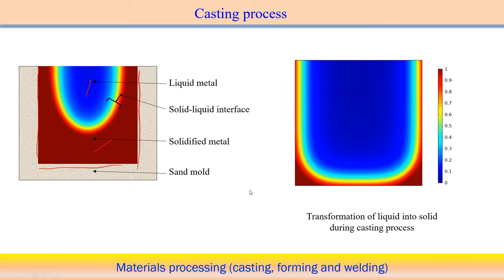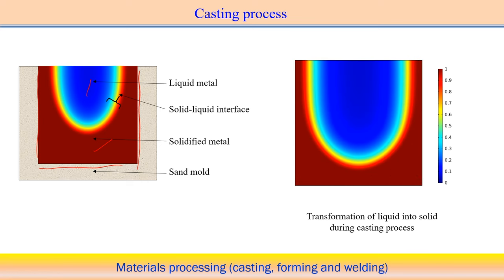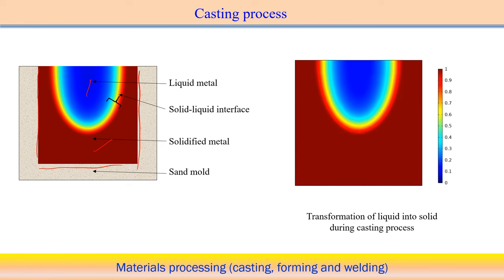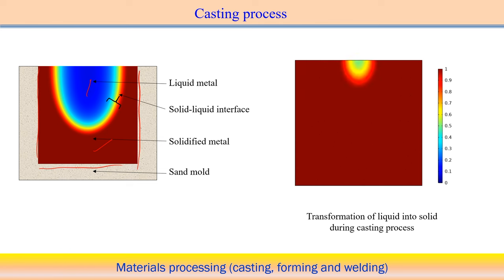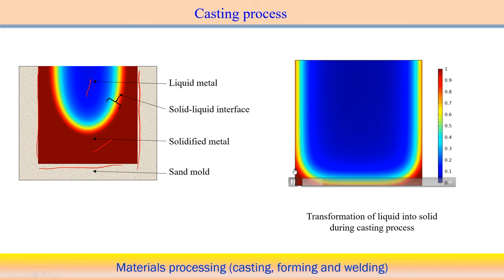If you see the domain at one particular instant, this is the solidified part, this is the liquid part, and they are separated by the solid liquid interface. And there is a transition in temperature across the solid liquid interface from liquid phase to solid phase. It is a gradual transition, not a sharp transition in this case. So we can see the simulation of how we can represent the casting process. You see that it gradually starts solidifying from the corner, the surrounding wall, and moves towards the center point, and at the end it moves very fast, and now it is completely solidified. So it starts with the surrounding wall where the solidification starts.